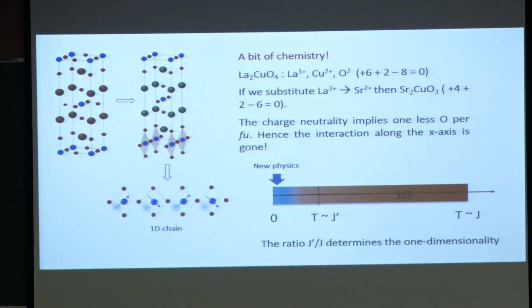So, if I replace lanthanum by strontium, I should remove 1 oxygen from the formula unit, and that affects the structure in a very interesting way. So, the oxygen from the XY plane or the AB plane of the crystal structure. You see the oxygen sitting here. This oxygen is no more there in the strontium case. So, this oxygen is gone from here.